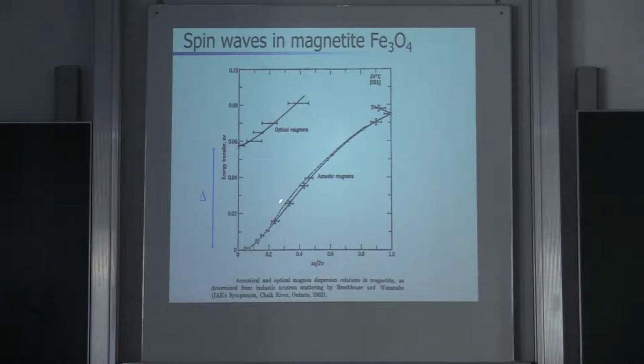Now we see there is a nicely almost parabolic dispersion, which corresponds to the ferromagnetic acoustic magnons, and the optical magnons here are at a much higher frequency. And this delta here is the exchange energy, this exchange splitting. Now, if you look at kT, which shows you how much of these magnons are occupied according to the Planck distribution function, then you see that's about here.